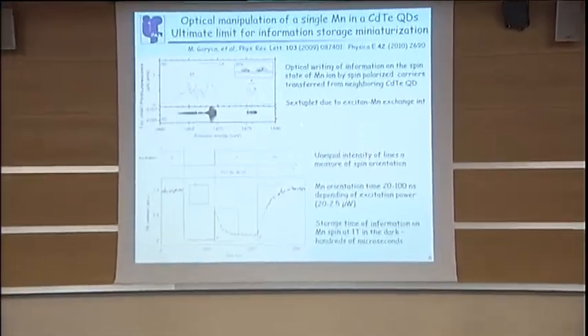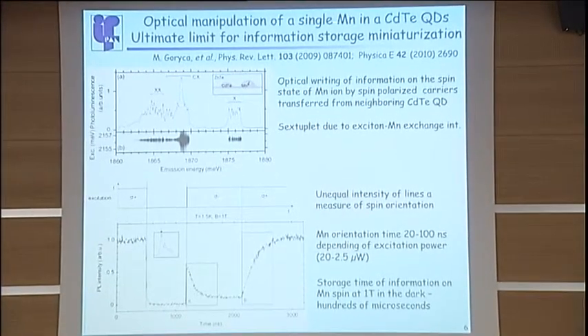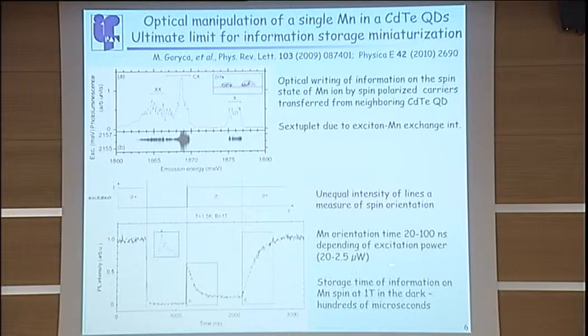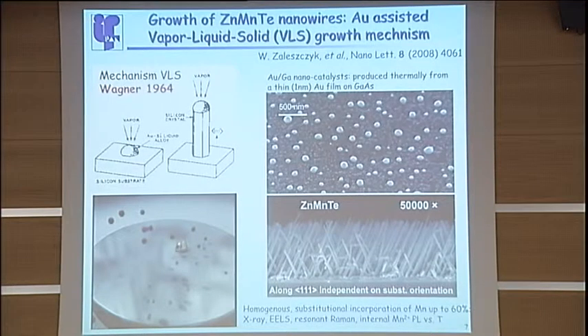So just one slide about the quantum dots, because we already have heard about them in the previous talk. I just want to mention that a single manganese atom can be thought of as an ultimate limit for information storage, and our colleagues from Warsaw University showed that the storage time on single manganese ions can be as large as hundreds of microseconds. Now, you can also cast those diluted magnetic semiconductors in the form of nanowires, and this can be done using the so-called vapor-liquid-solid growth mechanism proposed by Wagner in 1964. And the idea is very simple.